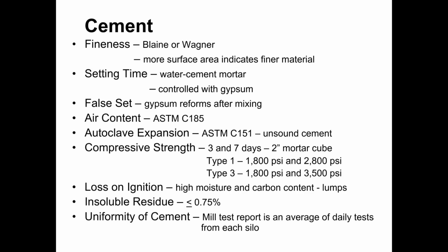Compressive strength is also indicated on the mill report. The compressive strength that's indicated is the result of 2-inch mortar cubes. So again, no aggregate is involved. It's just a cement water mortar, and 2-inch cubes are tested. Whether the cement is a type 1 or a type 3, there are different requirements for what minimum strengths should be attained and over what period of time. Just like the setting time information is provided so that you can make a relative assessment between different cement samples, it is the same thing with the compressive strength.